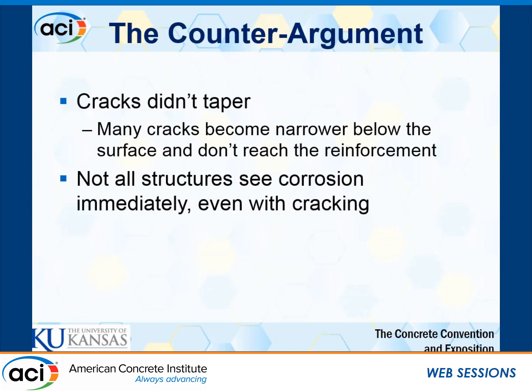A counter argument to what we're looking at from a corrosion standpoint is that a lot of these cracks tend to not taper with those experimental setups, whereas if you look at it from a bridge deck standpoint, those do tend to taper. You have a wider crack at the surface, and that may narrow down or even close up just below the surface of that concrete. So if you have 3 inches of bar cover, you may not have to worry too much about that, but that's kind of hard to quantify or actually observe if you're standing on that bridge deck.